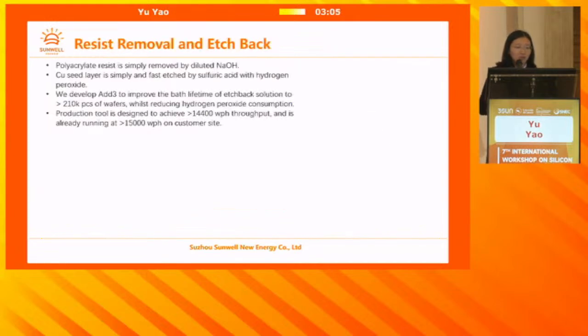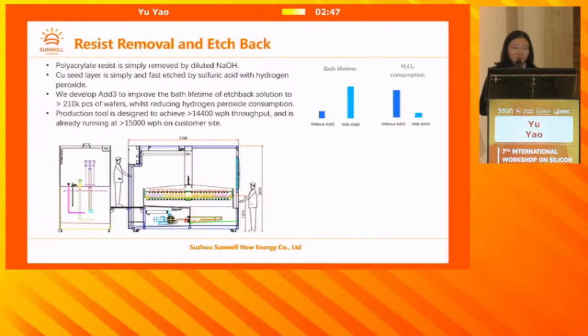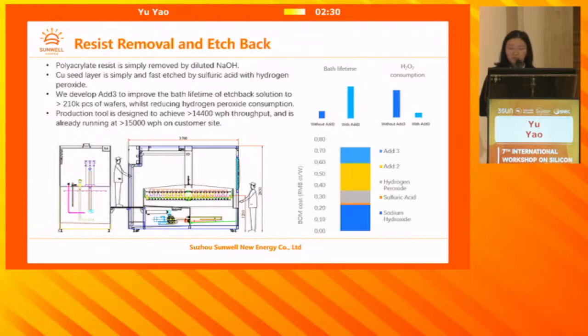And going to the resist removal and etch back, it's a polyacrylate resist, so it can be very easily removed just by diluted sodium hydroxide. And the copper seed layer we can fast etch by sulfuric acid with hydrogen peroxide. And we have developed an additive to improve the bath lifetime, and at the same time it's a stabilizer for the hydrogen peroxide, so we can reduce the consumption of hydrogen peroxide. And the tool we have on customer side is already running at more than 15,000 wafers per hour.